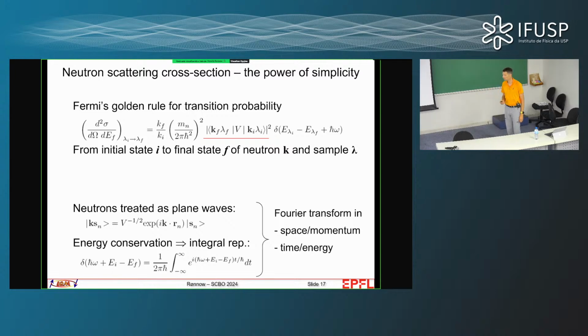Okay? Now, the neutron I can write down as a plane wave. So an incoming plane wave, an outgoing plane wave. And basically once I have this thing here, what I end up with is a Fourier transform. So that means that the fact that I treat the neutrons as plane waves means that up here I just get a Fourier transform of this interaction with the sample. Okay? We also have to have energy conservation.